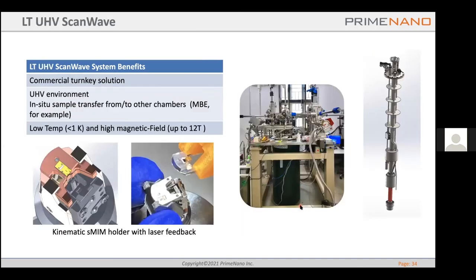And for the UHV system, we have the low temperature UHV scanwave system. It's a different system where the sMIM is integrated into the UHV condition and connected to the other chambers, for example, an MBE chamber, and people can just grow the sample in this MBE chamber and, in the UHV environment, transfer it to the sMIM chamber and cool down to low temperature with magnetic field to do the AFM and the sMIM measurement. We also have the load lock that you can use to load other samples and to do quick sample probe exchange. With this equipment you can connect more MBE chambers or other SPM chambers, whatever you want, and it can reach a temperature below 1K and a high magnetic field up to 12 Tesla.